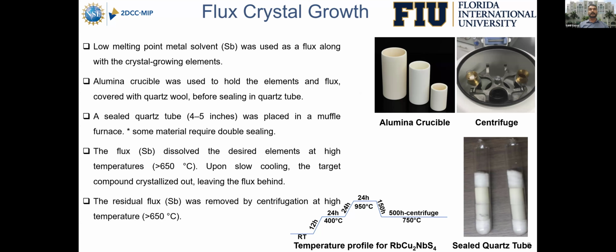So for this particular method, we need alumina crucibles, and we pour all our elements in that and then load this alumina crucible inside the quartz tube, as you can see over here. And on top of that, we put some quartz wool. Similarly, the size of these quartz tubes is around 4 to 5 inches long, so that we can easily put it inside the muffle furnace.